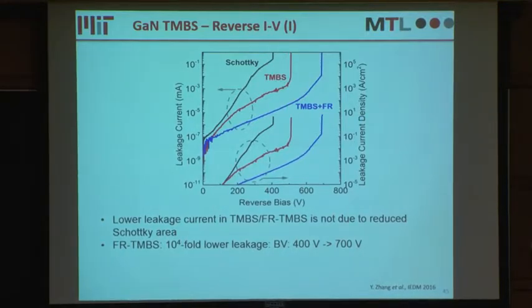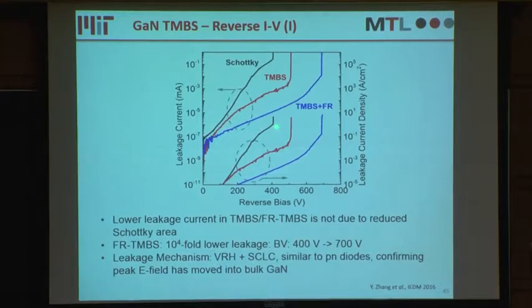Looking at the leakage current density for the 3 devices, the TMBS with field rings can have 4 orders of magnitude lower leakage current and increase the breakdown voltage from 400 volts to 700 volts. So the reverse characteristics have been greatly improved.